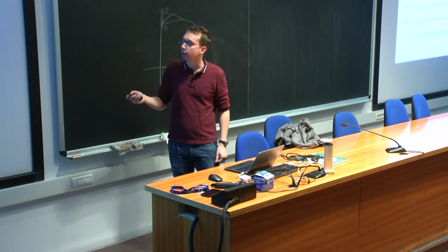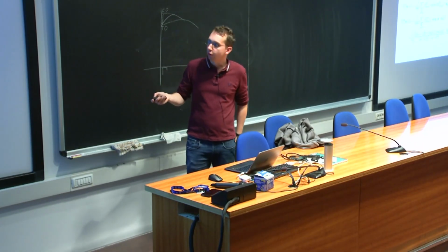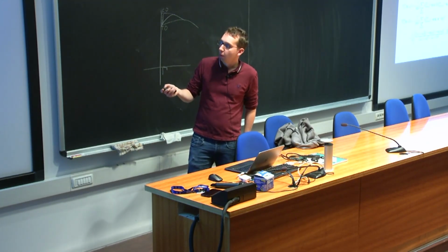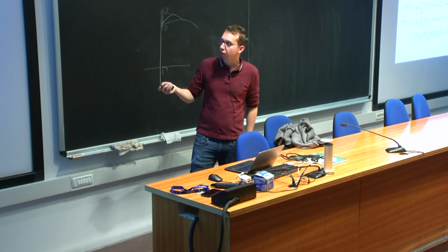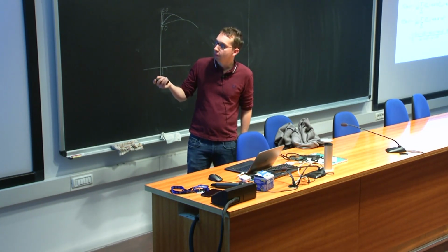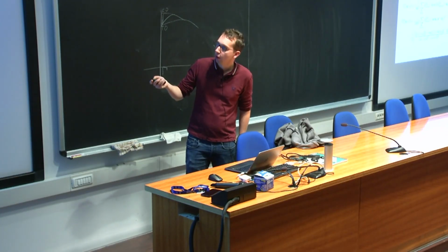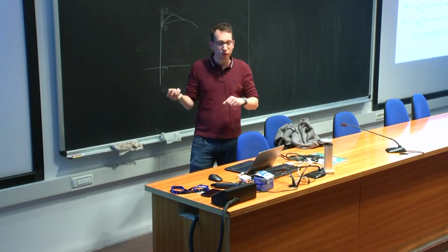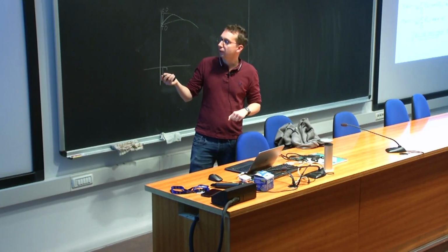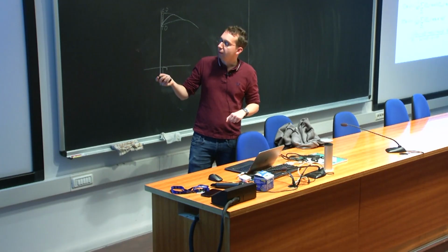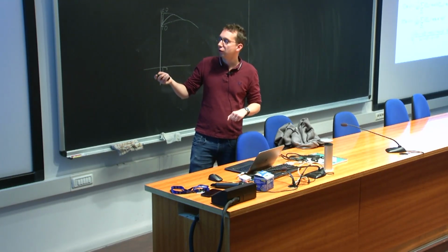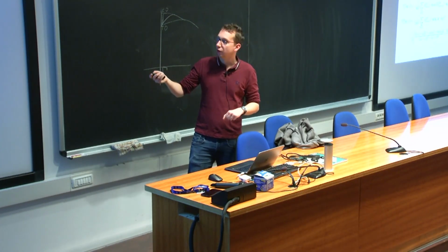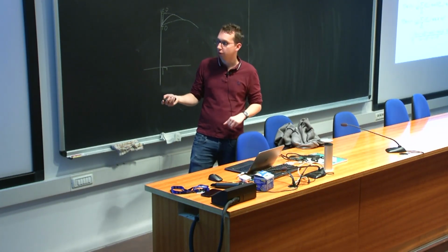These are the mathematical formulas for these terms. The tadpole, we say we don't care, we can do it in the quasi-harmonic approximation. For the loop, you have the fourth derivative of the energy, and you take it at the phonons with plus and minus q, so it is a bit of a special case, and multiply it by the Bose-Einstein occupation of the phonon energy, and it gives you a quantity which is real. It's a real number, and is a shift in the phonon frequency.